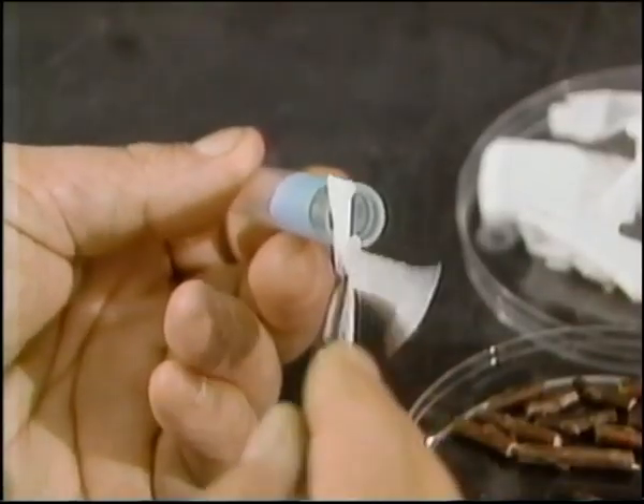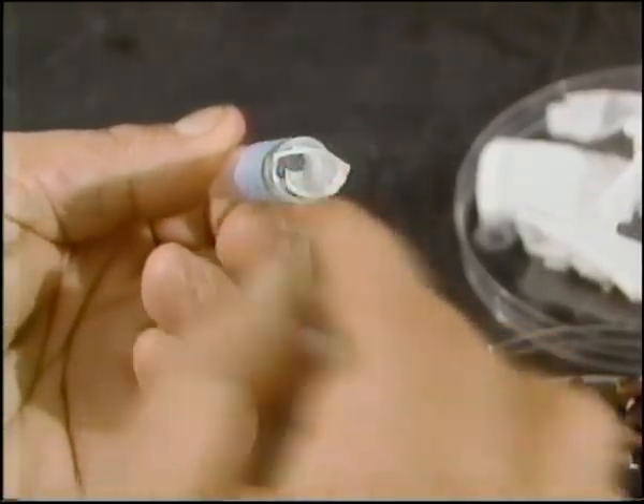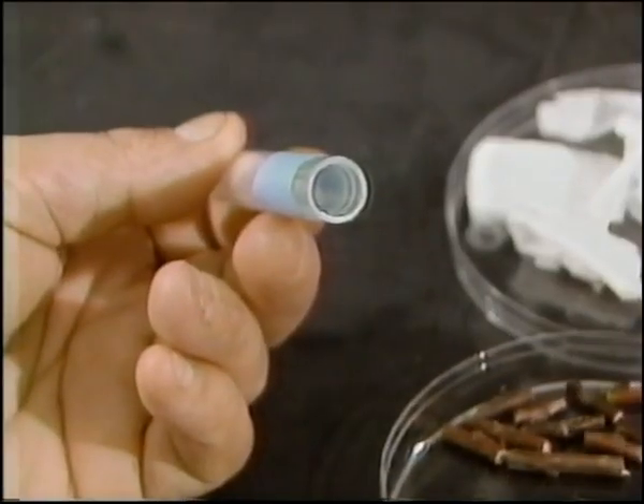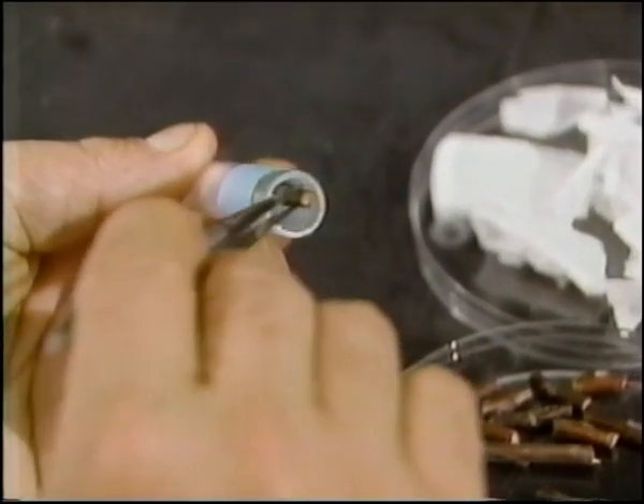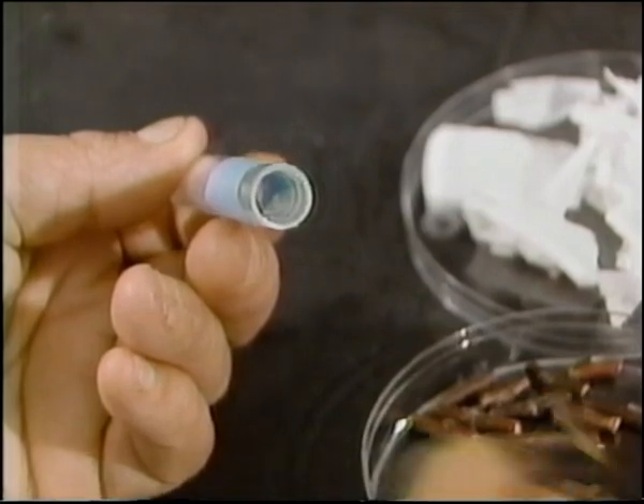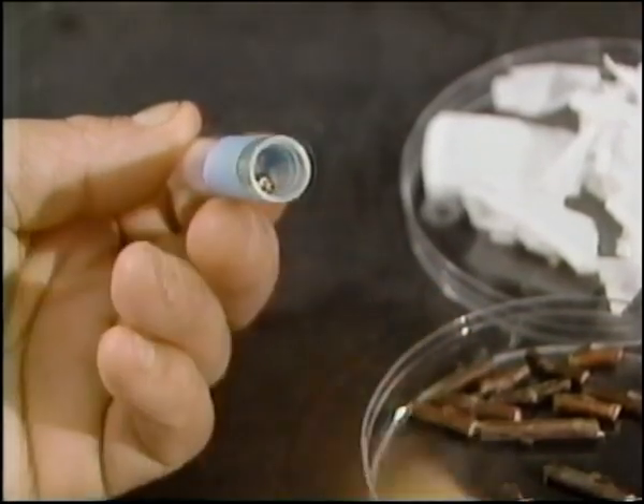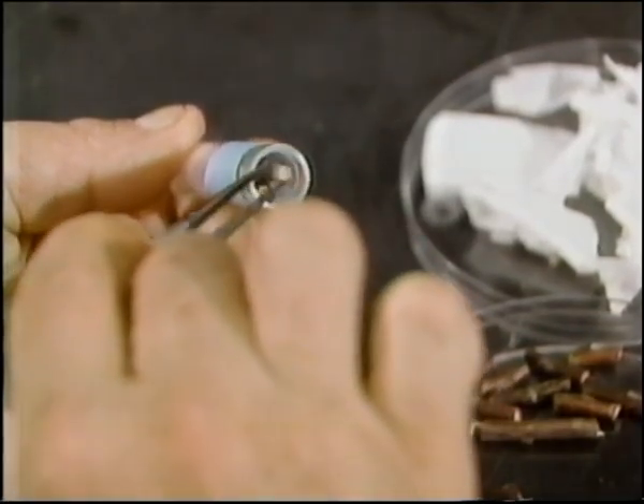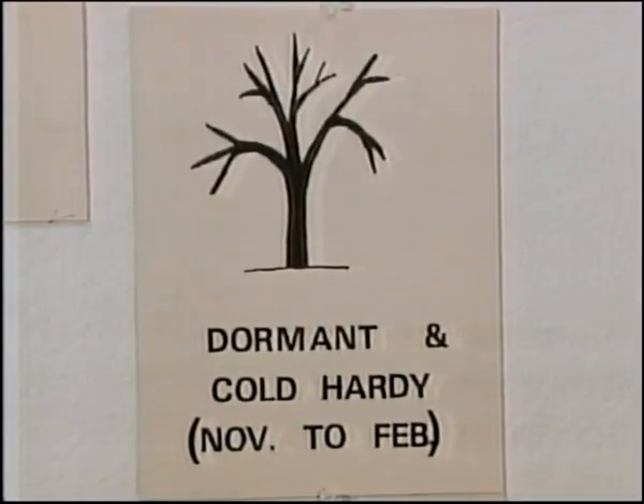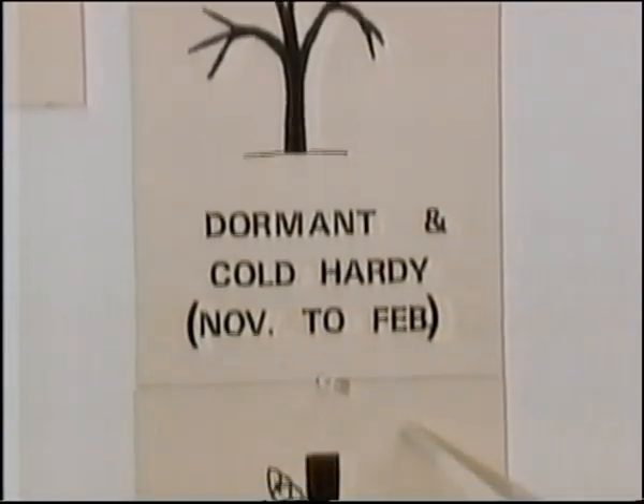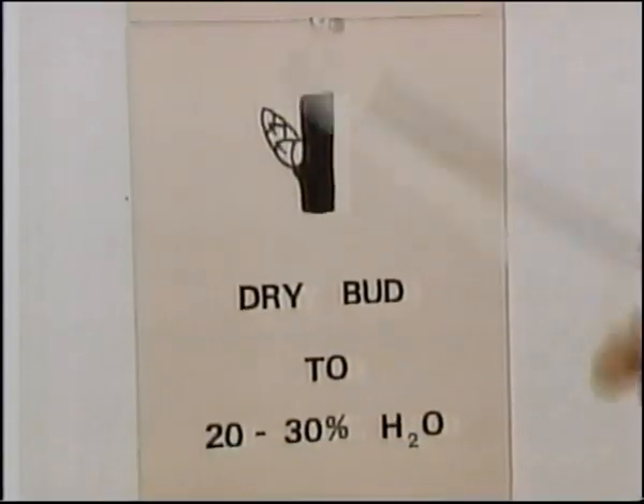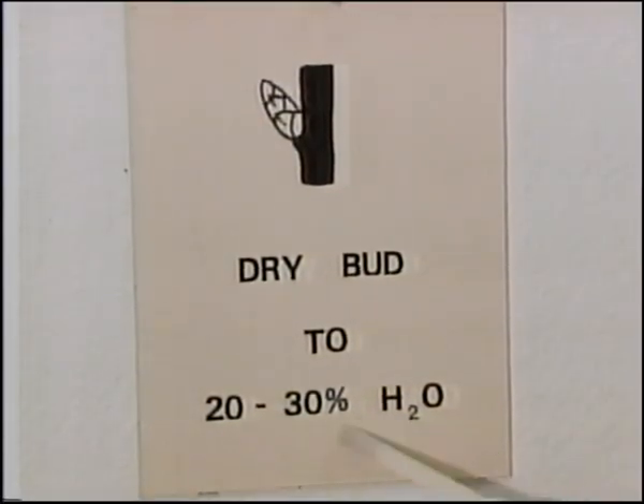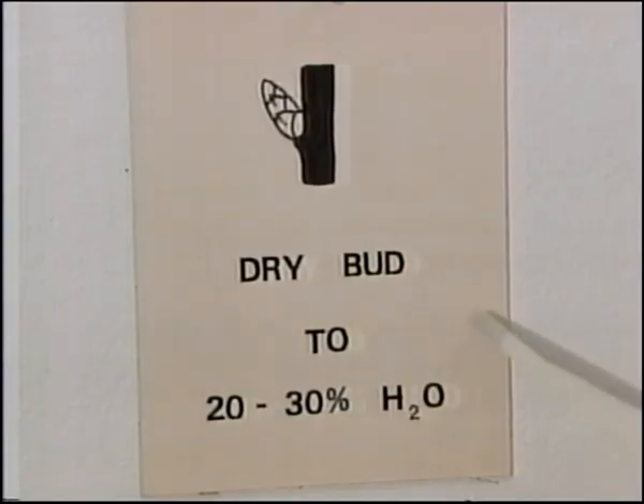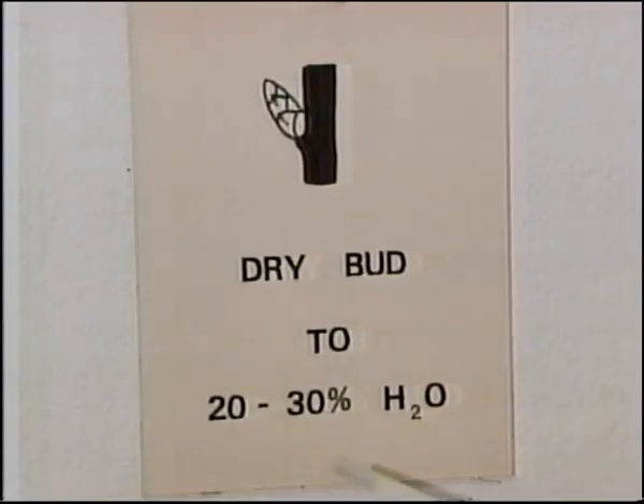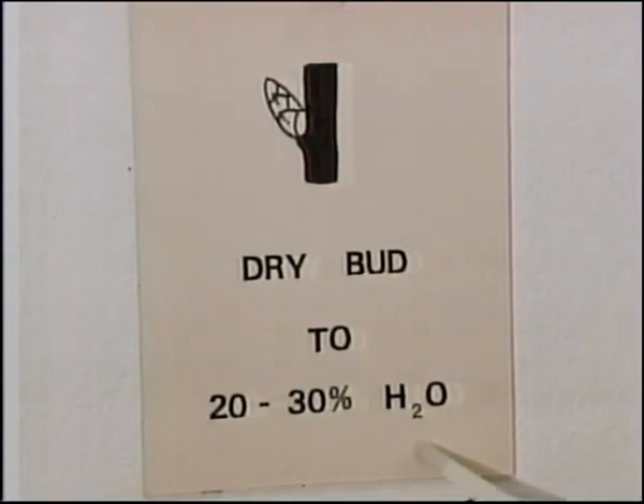The first of these is to take the bud from a dormant tree. Trees that are outdoors from November to February are dormant and they're cold hardy. This means that they will withstand temperatures down to -40 in this part of the world under these circumstances. That's the first prerequisite. Secondly, then, the bud is taken from the tree and dried to 20 to 30% water. In the field, the water content is 50 to 55%, and it must be dropped to about 20 to 30% in order for this process to work.